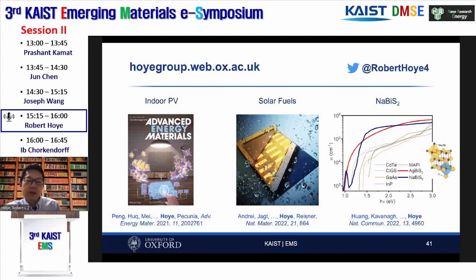And in addition to defect tolerance, I showed you in this latter half of the talk the importance of considering carrier localization. Because historically it's just been assumed that a very long lifetime is good for solar absorbers. But here we show that it's not necessarily the case if you're dominated by carrier localization. And this is a process that isn't so well understood so far. So I think it's also very important that we develop new fundamental insights into what design principles, what chemical descriptors, allow us to identify whether materials will undergo carrier localization or not, in order to help us to design materials that can avoid this property. So I think in the future, we need to find the intersection between defect tolerance and delocalized charge carriers.